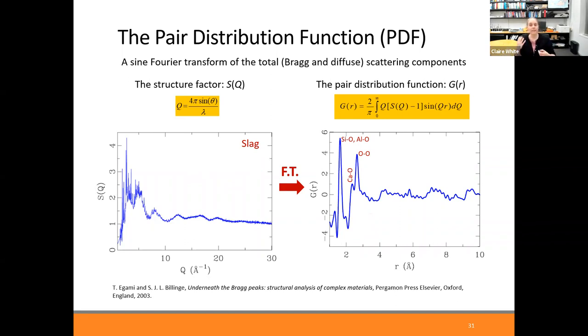And so it shows you bond lengths, and then it shows you longer range distances between atoms. And so for something that's predominantly amorphous, which is the case here, a calcium aluminosilicate glass, you've got your bond lengths, and then you end up with some medium range ordering. But once you go out to large distances between atoms, there's no ordering. And so you'll just have the data sitting at around 0.